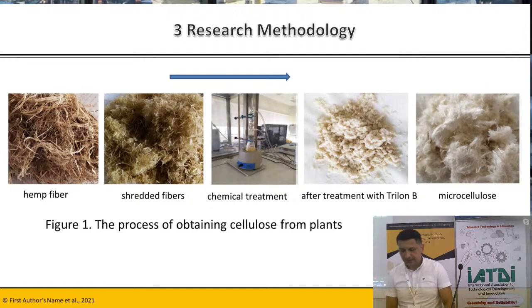The process is carried out in a heat-resistant flask, a mold of flask, with a heater connected to a reflux condenser. After obtaining cellulose, it's the last picture. We use a laboratory homogenizer, and after that, the crushed cellulose was filtered through filter paper and then dried at room temperature.